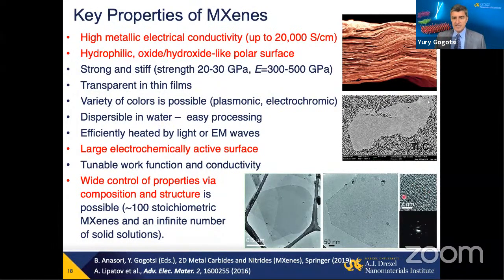But if you look at the high resolution TEM image or electron diffraction, you will see those flakes are single crystal. So a single layer, single crystalline material here, but with very high mechanical strength and stiffness inherited from transition metal carbides and nitrides. Of course, they are, as I mentioned already, hydrophilic, soluble in water. So just this combination of properties already gives many interesting advantages for applications.